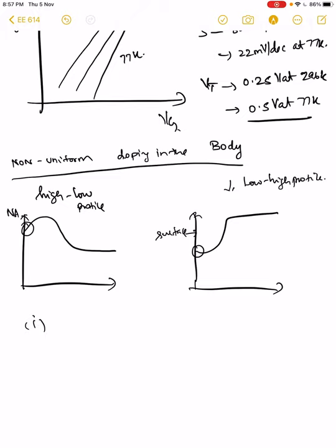Both of them are used depending upon the application. We'll just discuss the positives and negatives of each one of them. You have lower doping at the surface typically because you want to improve mobility. At the surface, what happens if you have ionized donors? The ionized donors will scatter. We saw previously that you have scattering by phonons and scattering by ionized impurities, right? So typically you want as low a density of ionized ions at the surface, and hence you always want to reduce the dopant density at the surface to improve mobility.